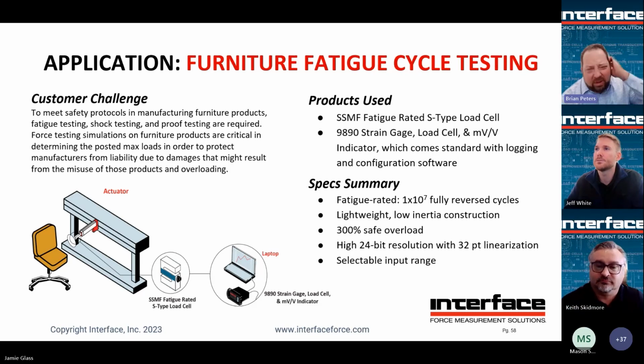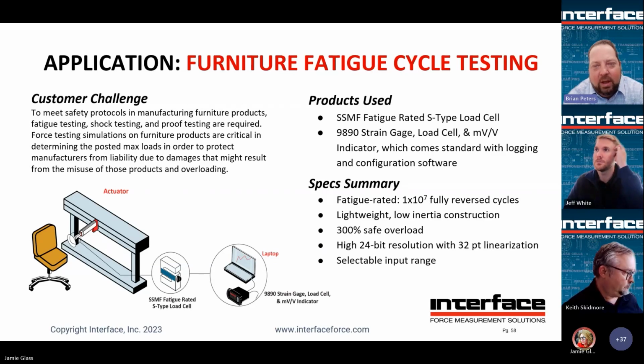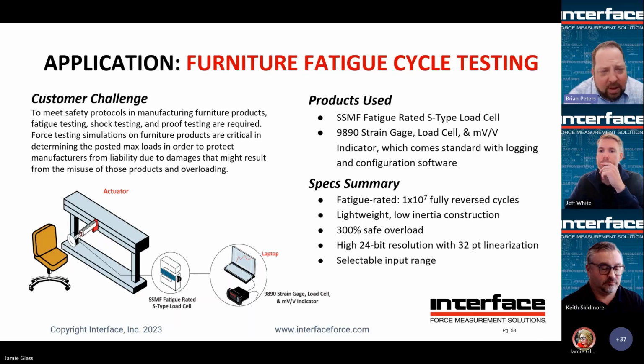So here's a high cycle fatigue test application. In this case, it was furniture testing. Again, most of you probably know how almost every single thing out there gets tested. In this case, choice was an SSMF. There's a fatigue rated S cell, well suited for high cycle testing. In addition to that, it's low weight, so you're not adding a lot of inertial element to your cycle testing. Good safe overload too, 300% safe overload.